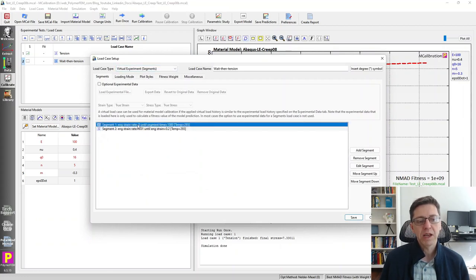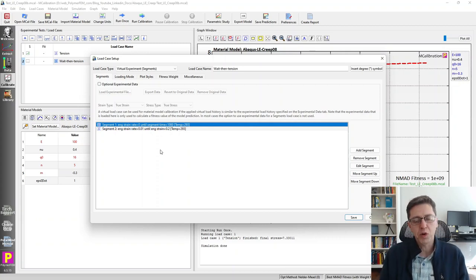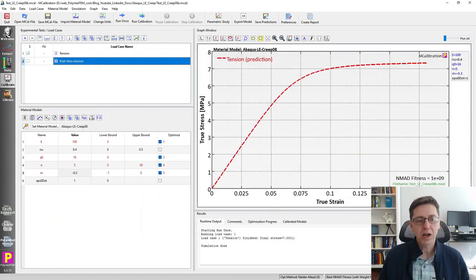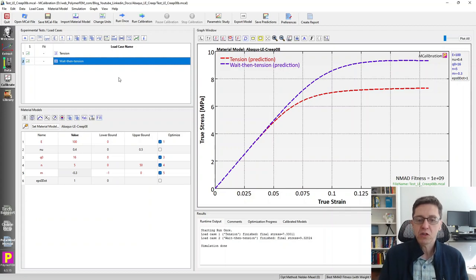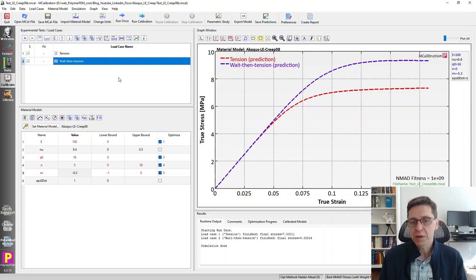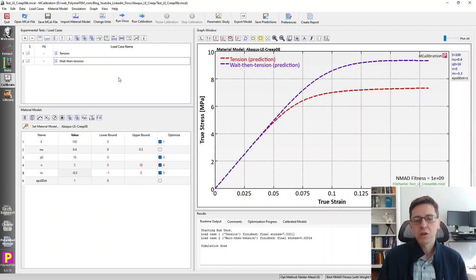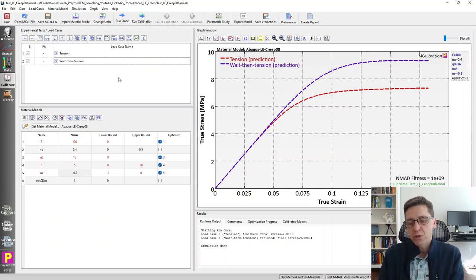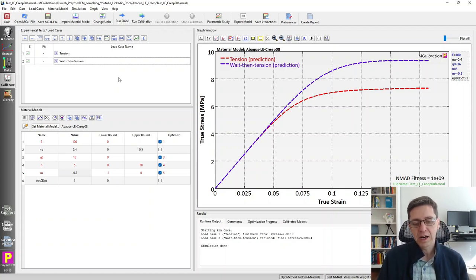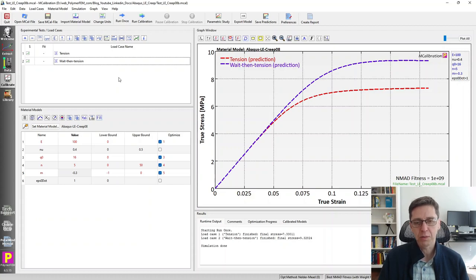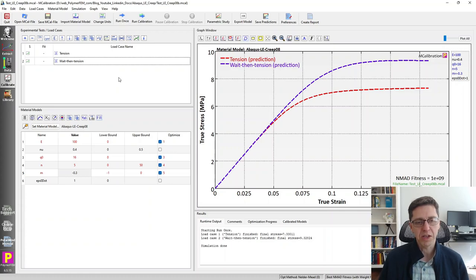But the trick here, which you really need to remember, is that if you do a different experiment simulation here, a virtual experiment where I keep the strain zero for a thousand seconds, and then I deform it. So basically saying, I'm going to keep my specimen just sitting here on the table, and then I'm going to deform it, I will get a different response than if I start deforming it right away. So a specimen that sits there under zero strain or stress actually will behave differently, because time has changed. It's really goofy in some way to have a stress that depends on time, and it doesn't matter what strain was. So that's really what you get with this kind of model, this weird time dependence. So what people do when you try to use this one is that any load step that does not have load, make it really, really short, and then the real creep is just where you focus your effort. But it's a little dangerous because clearly you shouldn't change the response of the material when it just sits on the table under zero stress or strain.